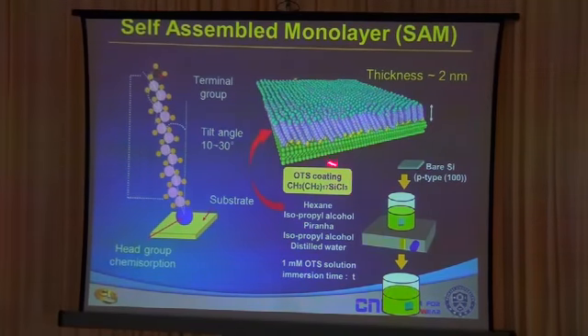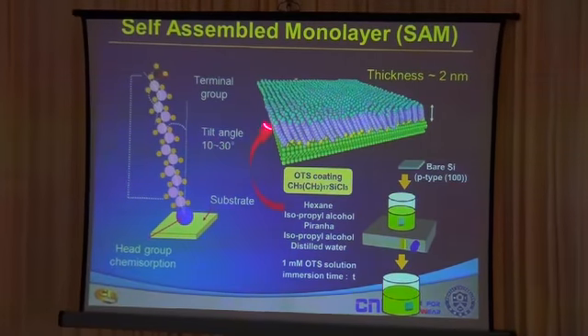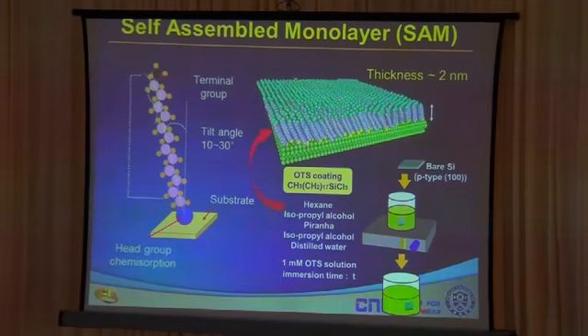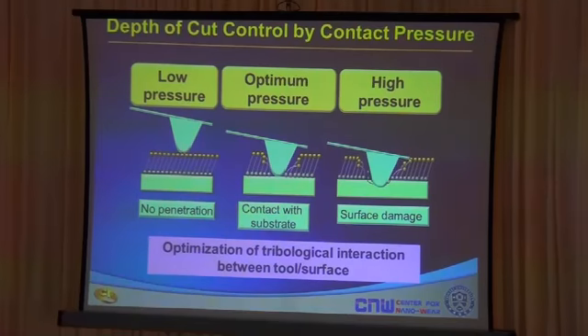In the end, when you coat this kind of chemical on your silicon wafer, simply by dip coating, you're able to align these molecules very well on the silicon surface. And it's called self-assembled monolayer because it automatically aligns to a very stable and minimum energy state, which is represented by the schematic here. So, using this particular resist, what we want to do is to remove just the 2 nanometers of resist from the silicon surface.